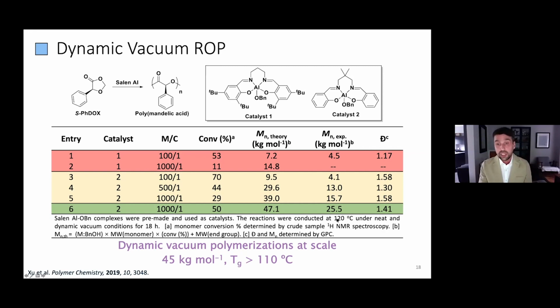And so if I just look at these systems with those conditions, I now can get up to 25.5 kilograms per mole, right, which is near where our target needed to be for our industrial partners. We have a partner in the United States that has now done this at scale and gotten 45 kilograms per mole, giving us a polystyrene mimic. And so the reason we started with this polymandelic acid is we wanted to get up to high glass transition temperature species so we could potentially replace polystyrene in packaging applications. And that gives us a glass transition temperature of about 110 degrees, which is perfect for the space that we're working in.